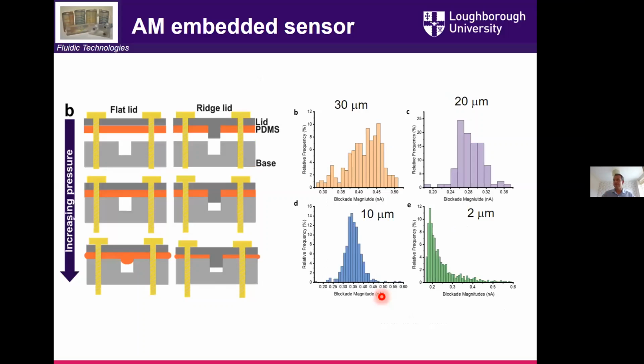The real cheat for us in this was not just to use a flat lid, but to use a lid with a ridge on it, so that that ridge sat within the channel with the same PDMS layer. You would then increase the tension of the screws, and that ridge would creep into the channel. And if you increase the tension of the screws enough, you can effectively block it. It becomes a valve and shuts off the sensor. But as you change the screw tension, you can change the size of that flow channel and change the sensitivity.